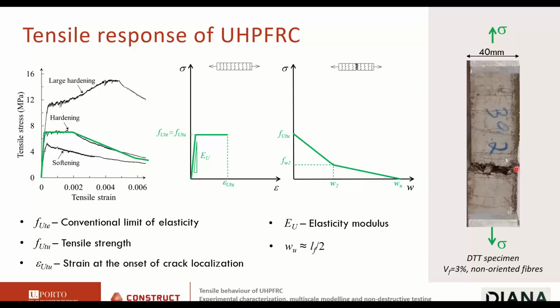So when we have this type of behavior, a bilinear curve also models the tensile response prior to localization here, but typically a horizontal branch is good enough to reproduce what we see in the tests.